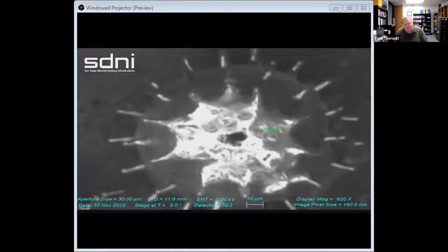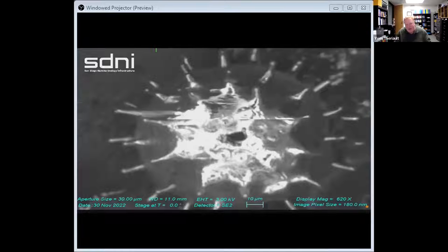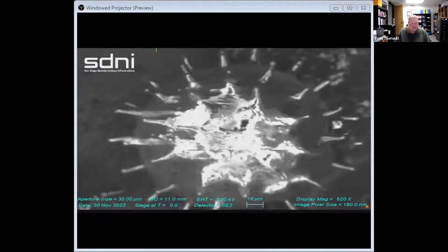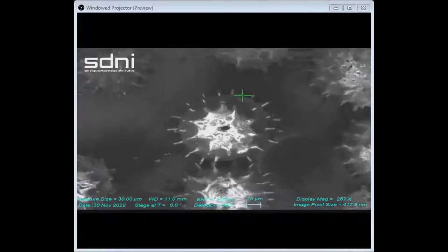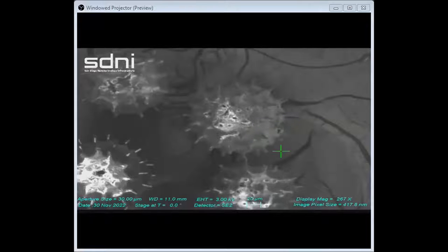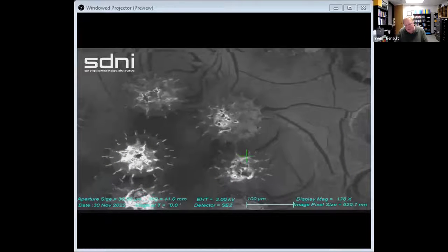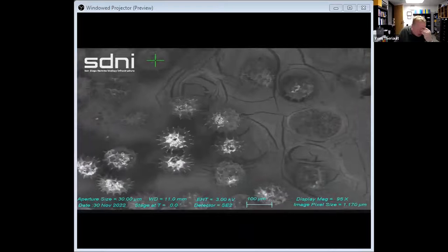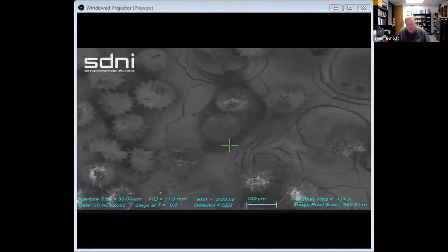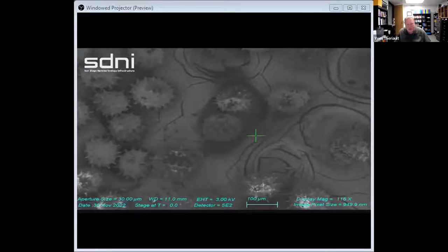It depends on the material itself. Sometimes the samples will absorb a lot of energy, and then you have white reflections like that. So you need to avoid that as much as possible. Especially organic samples, we get these images by shooting electrons down at the samples, and a lot of organic samples, like pollen included, don't conduct electricity on their own. So yes, we sputter coat them. That's something we didn't mention, is that the biosamples are first dried and then we also coat them with some metal so that the surface can be appropriate for an electron microscope.